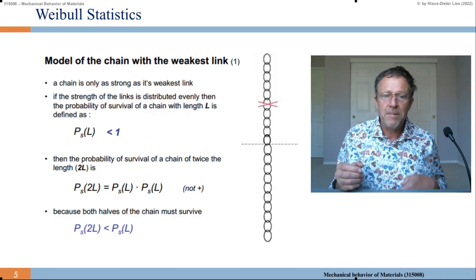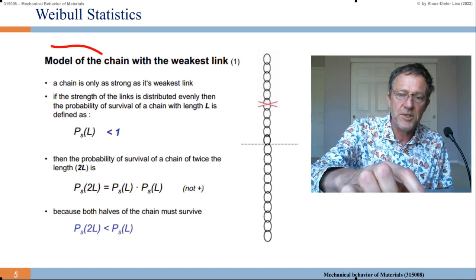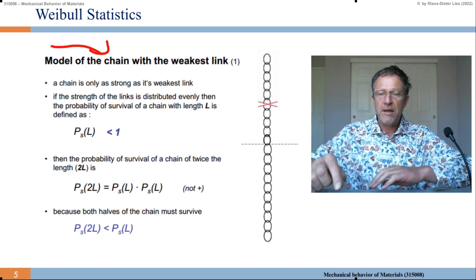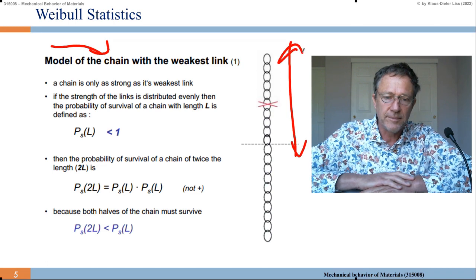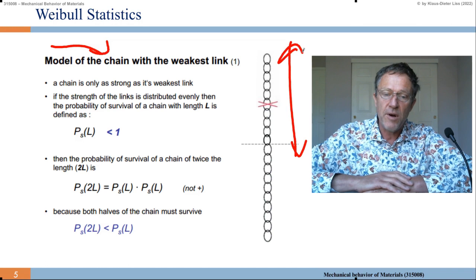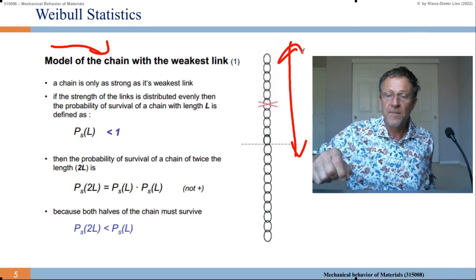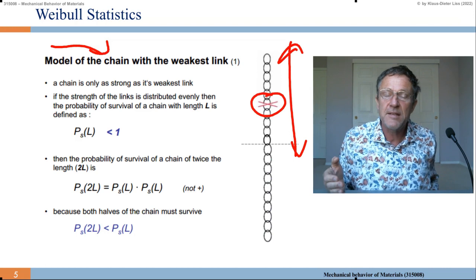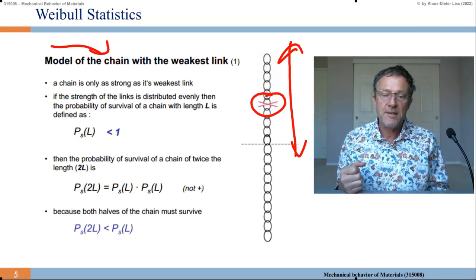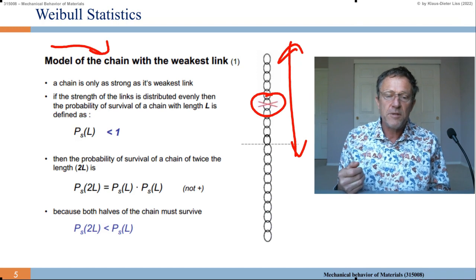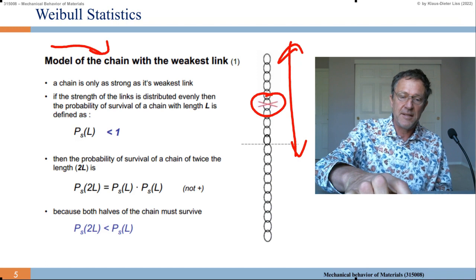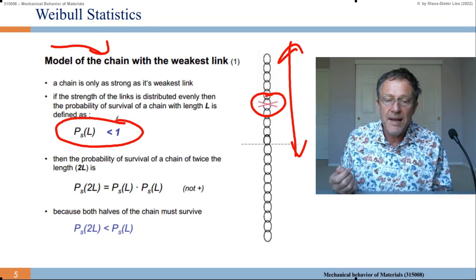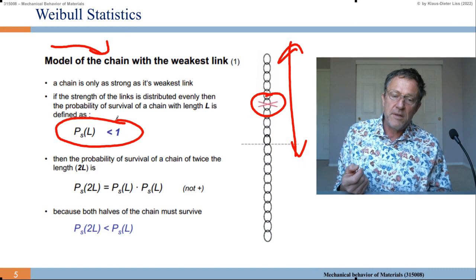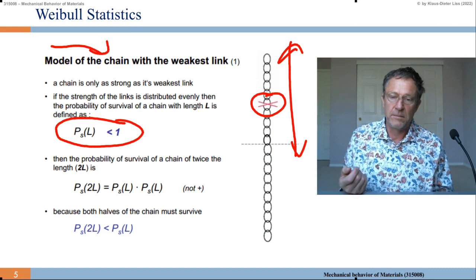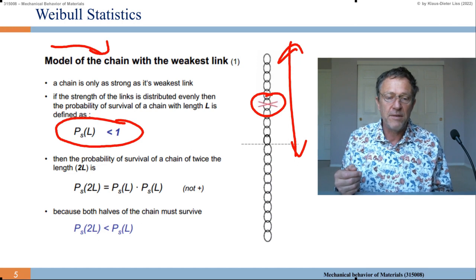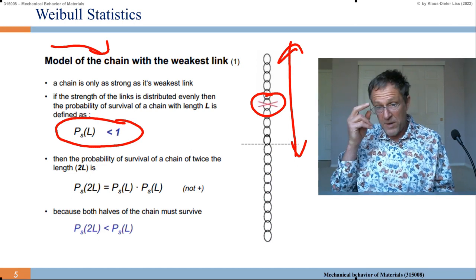So, let's set up a model, namely the model of the chain with the weakest link. If we consider a chain of a length L, then the chain is only as strong as its weakest link. So when we pull that chain and we have the weak link here, then it will break at the weakest link. If the strength of the links is distributed evenly, then the probability of survival of a chain with length L is defined as some probability of survival P_S of L, which obviously should be smaller than 1, because if it's 1, then it's trivial, it always survives, you cannot break it. And it's smaller than 1 if you apply some stress.